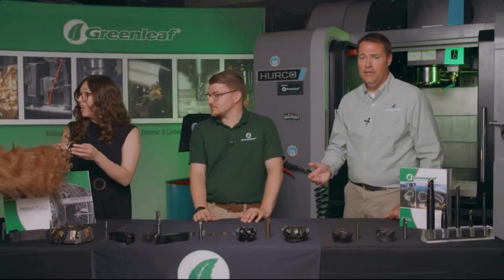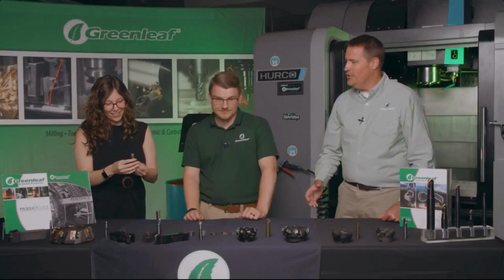While ceramic end mills cannot be reground in the same way that carbide tools can, they can be resized. It is important to note that it reduces the overall length, but it does restore the function of the end mill. That's true, but in the case of our new product, Capstone 360, you do not look for wear in the same way you would with carbide tools. Instead, you wait till the sound of the machining changes or you see a sudden spike in the spindle load. As long as the chips are generating the same color, you can assume that the machining is properly set up.